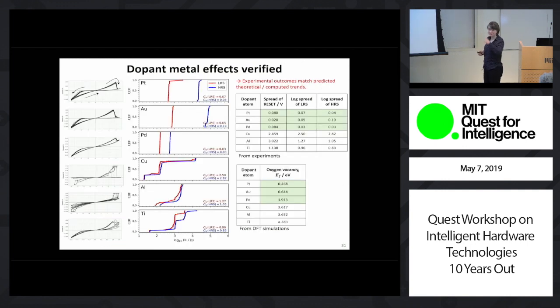So we experimentally went ahead and validated this. Now I'm showing you the cumulative distribution functions for the range of obtained resistances, and similarly we have results for the reset voltages, and you can see a much tighter distribution with gold, platinum, and palladium, and a much broader distribution, so less controllability, more variability, with copper, aluminum, or titanium implanted into aluminum oxide. And that trend, these three atoms giving rise to better controllability, is consistent with the easier vacancy formation and easier vacancy accumulation around these dopants in aluminum oxide.